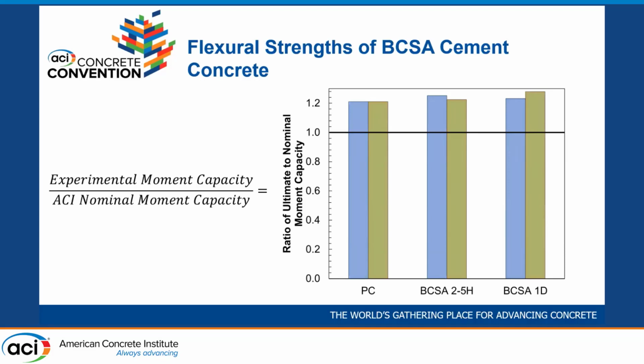Another way to compare these is to take the experimental moment capacity, the maximum moment that the beam achieved, and divide by the nominal moment capacity in the ACI equation or in the ACI code. And so a number greater than 1 here is a good thing. That means that our capacity exceeded the estimate or the predicted capacity. And you can see for all of our beams, we were around 1.2, including all the BCSA beams. They were quite consistent with the Portland cement.